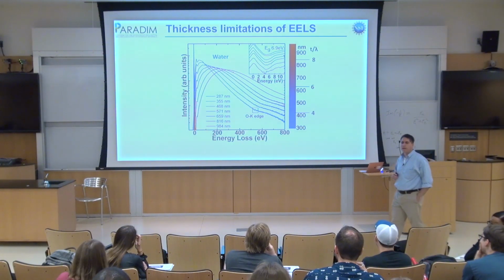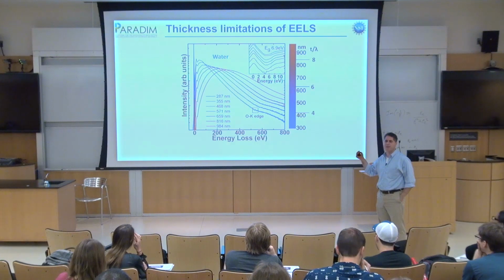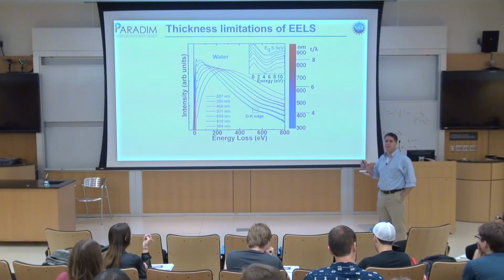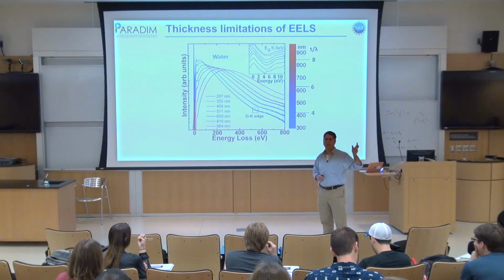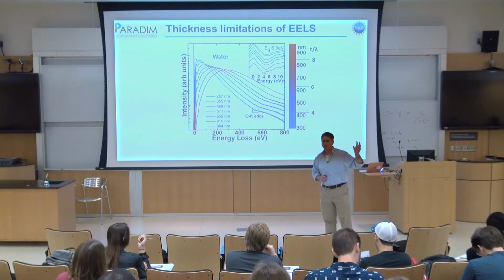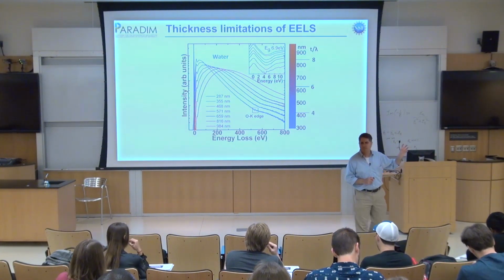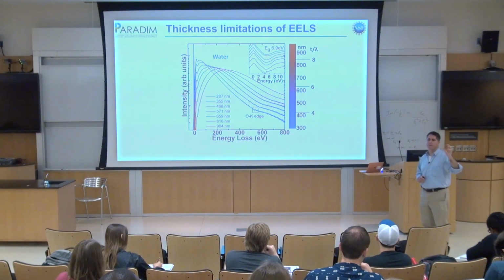It does, actually. If they get too small, you'll get into real trouble. And so I'm going to talk about what happens when they get small. The bigger the nanoparticles, the easier life is. I'll talk about the length scale at which you run into trouble with plasmons. And it's about 2 to 3 nanometers that things start to go very funny. You shouldn't trust the resolution below a couple of nanometers.